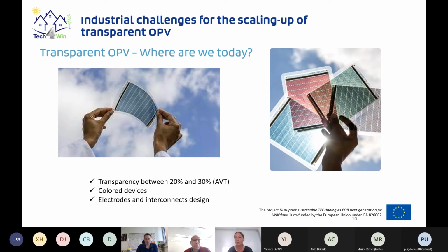So at this point, we already can do some semi-transparent OPV. It's quite a common thing on a semi-industrial scale. We can have some different colors, for example, blue, red, green, gray, but always we have color samples. We have a transparency that is for the AVT between 20% and 30%, depending on the architecture and on the color of the devices. So it's quite nice looking, but still not enough transparent to be integrated in a window.